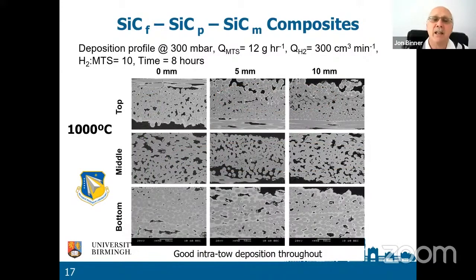And you can see here, these are the samples at 1000 degrees centigrade. The time is 8 hours. And you've got there, the center line is at 0 millimeters, and there's very little deposition. But as you move towards the surface, you get more and more deposition. So again, we're able to see from our samples that this whole inverse temperature profile works very, very nicely.